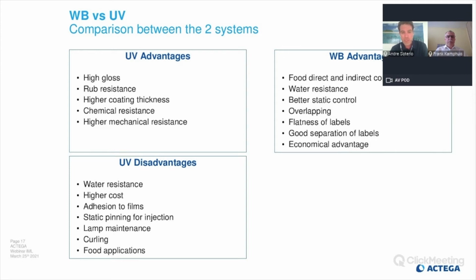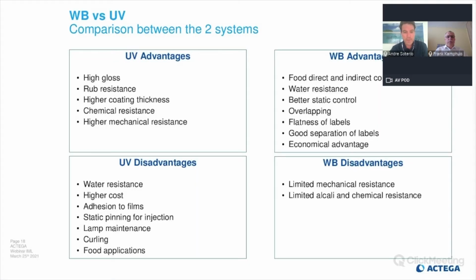Flatness of the label, which means you will not have curling. It depends a lot on the product, the coating used, and how you print it, and we're going to see later on the technical specifications. Again, a very good separation of the labels. You don't have a glass effect between the labels, and there is an economical advantage because water-based coatings normally cost less than UV coatings. But water-based coatings also have some disadvantages. As I said, limited mechanical resistance, especially rub resistance, and limited alkali and chemical resistance.